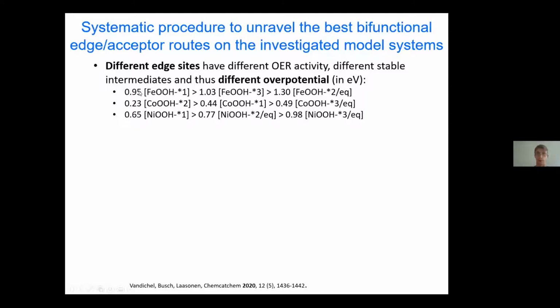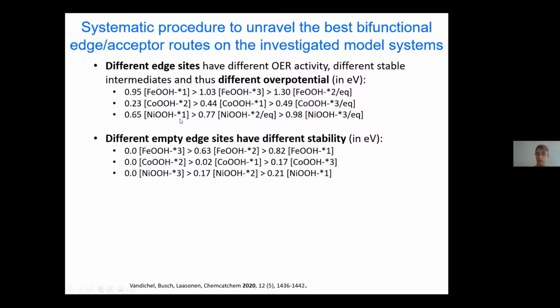So for iron, we find that this site star one is the best one. For cobalt, that is star two. For nickel OOH, that is star one. But even more important to know if they're relevant is to look at the stability of these active sites.